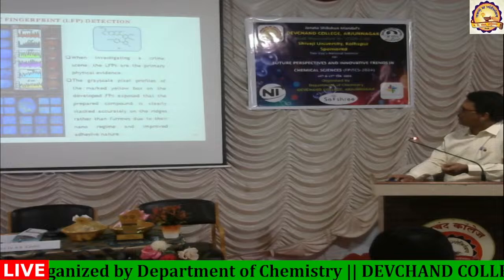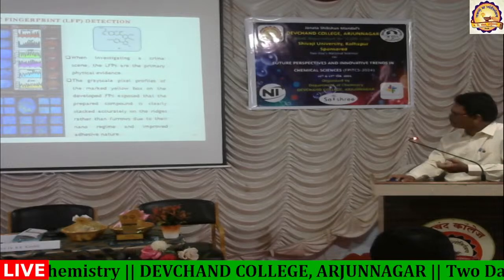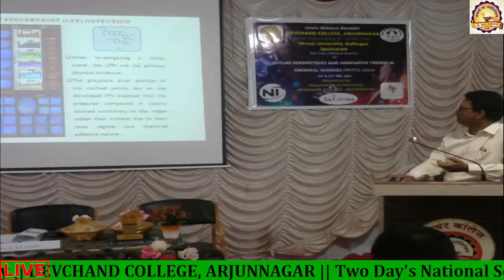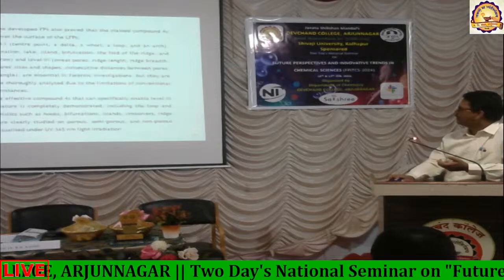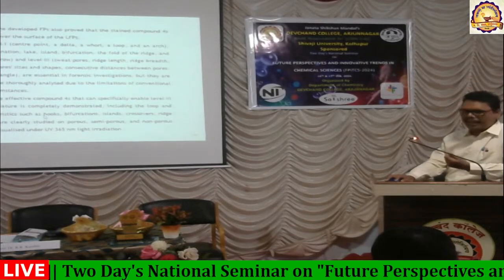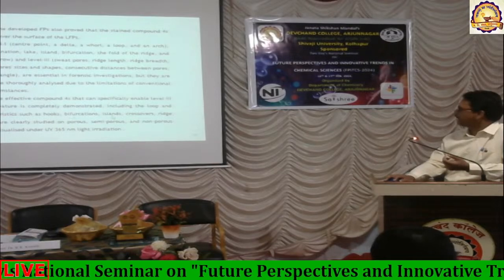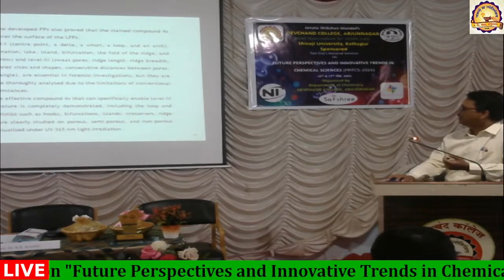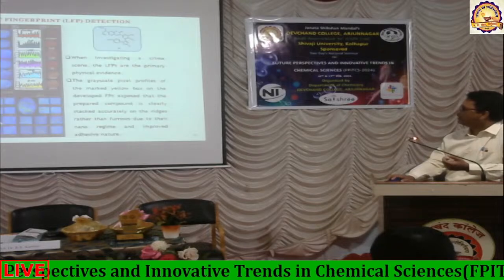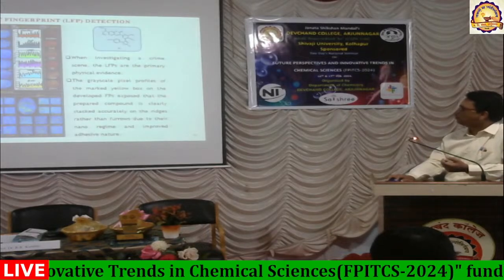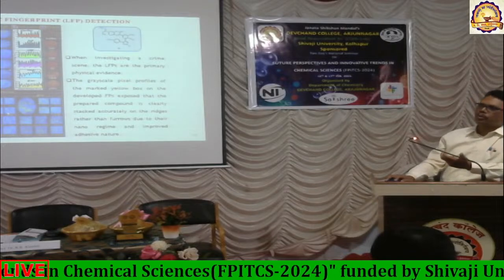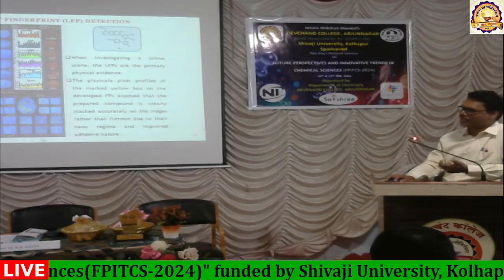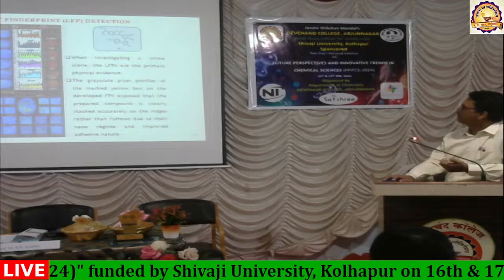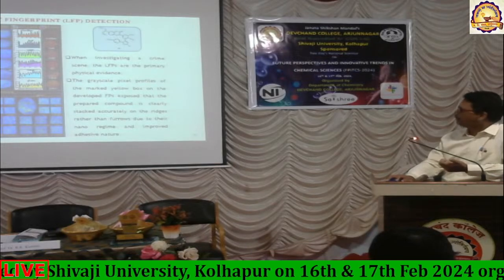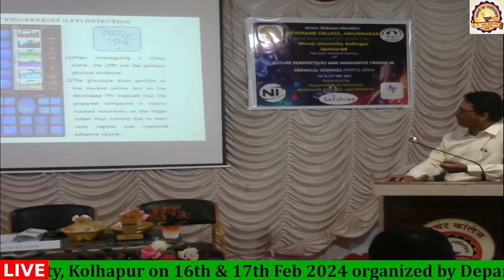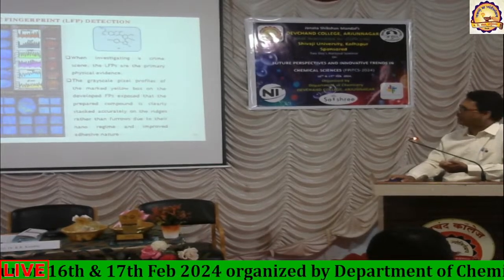But level 3 and level 4, where if we make more resolution, there are various kinds of places like the bifurcations in the lines of a fingerprint: hooks, bifurcations, islands, crossovers, regions, scars and dots. All these will be there, and these cannot be duplicated. Level 1, level 2 anybody can do, but these cannot be cheated. And even this fluorescent compound can be used for the identification of this, and even this can also be resolved very easily.